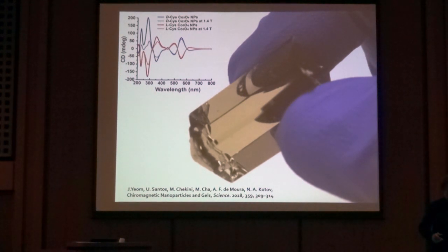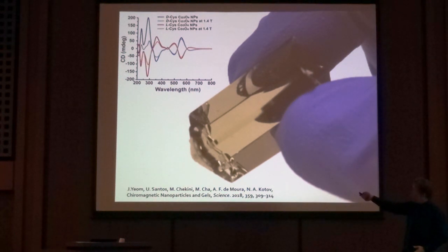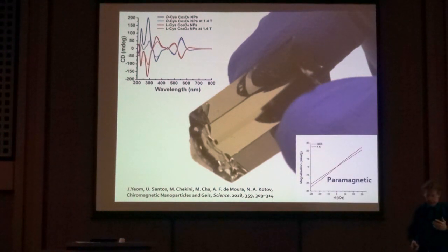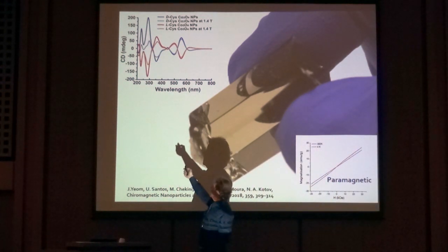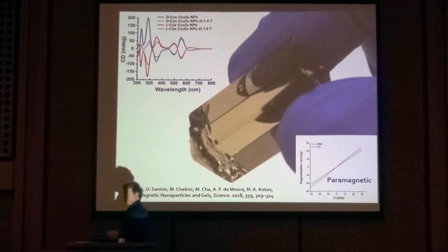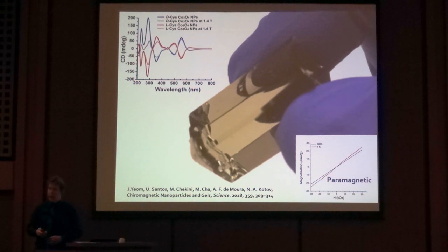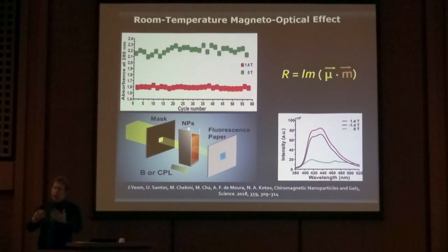Because by connecting these nanoparticles into chains and making hybrid materials, we can form transparent gels. The particles have distinct paramagnetic properties, and as we apply a field along the k vector of the light, we observe a very strong change in the transparency of the materials. So this is the translation into the magneto-optical and chiromagnetic materials, which can be observed by the modulation of transparency of these gels by application of the magnetic field.